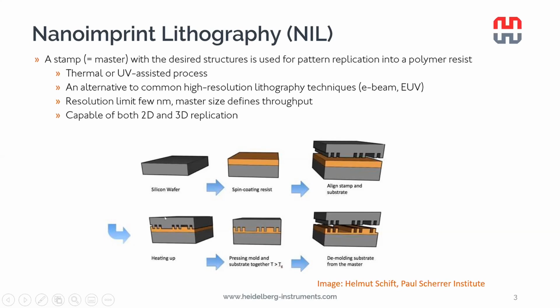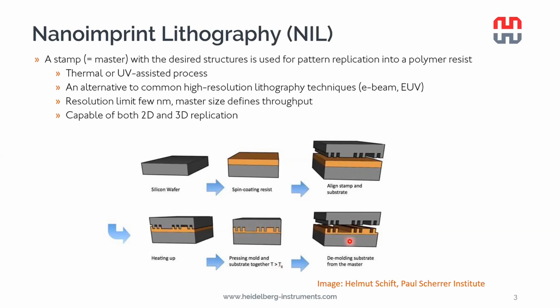So of course, if you want to press the stamp into the resist, it has to be either heated up above its glass transition temperature, or it has to be in a liquid form. And finally, the resist is either cured or cooled down, and we can then demold the substrate from the master. An important detail is that we always have a residual layer of resist remaining between the stamp and the substrate. This is for the sole purpose of preserving the stamp from any mechanical damage that may occur if it's pushed towards a hard substrate. The idea is that we can use the stamp as many times as possible to replicate as many copies of it as possible.